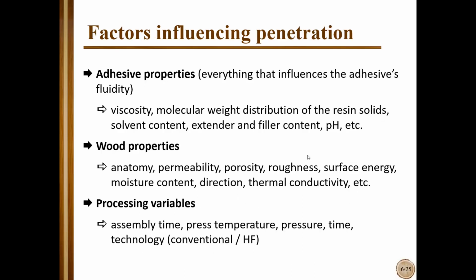Main factors that influence penetration are adhesive properties. I'm going to discuss a little bit about this on next slides. Then wood properties, and of course, processing variables, especially assembly time, open assembly time and closed assembly time. Then press temperature has a major impact. Also pressure. Pressure is actually the driving force for adhesive penetration. Time and technology. In these terms, I would like to mention conventional hot pressing in respect to high frequency or microwave heating, where adhesive curing is quite faster and different than in case of conventional heating.